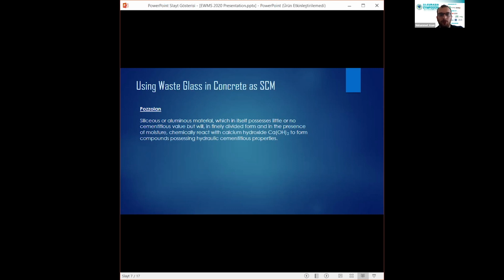To understand the pozzolanic reaction, we should first look at the hydration of the cement. During the hydration of cement, the calcium silicate components react with water and produce 2 products. One of them is calcium silicate hydrate gel. This gel allows the concrete to gain hardness and gain its mechanical and durability properties. The other one is calcium hydroxide. Traditionally, it's called slaked lime. Slaked lime is not required for concrete. When it comes into contact with water, it dissolves, causing voids in the concrete. It shortens the service life of concrete.